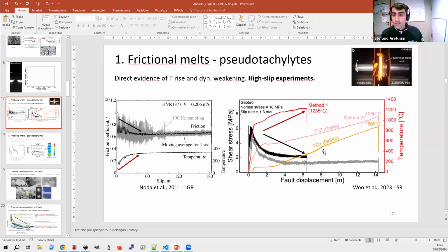We could see that the further your measuring point is, the smaller the temperature anomaly becomes. So heat production is very localized, but then with time it smooths down and diffuses away from the localization area. I think the heat source is actually very thin.